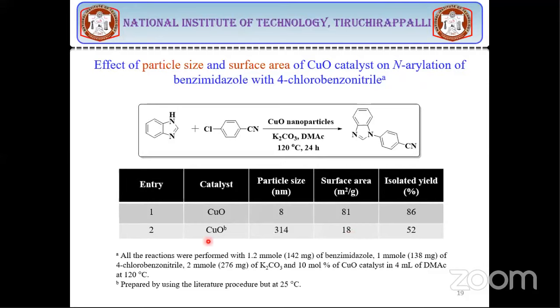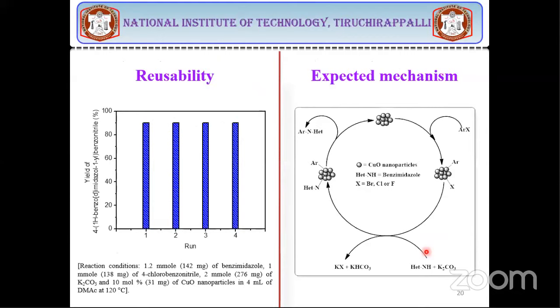When you use bulk copper oxide as a catalyst for the same reaction, you see the yield of the product is drastically reduced. It indicates that the nanoparticles, or the nano copper oxide, efficiently catalyze the reaction compared to bulk copper oxide, right? So that indicates the importance of nanomaterials in catalysis, or the efficiency of nanomaterials in catalysis.